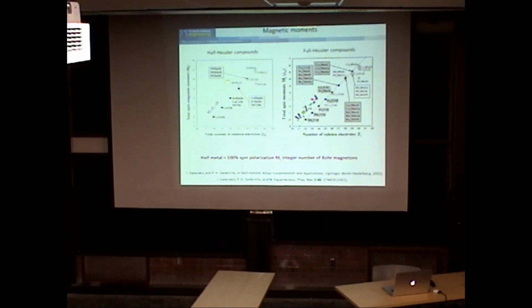You can go further. If I wanted a half metal, that means it should have an integer number of Bohr magnetons per formula unit. If I take the number of valence electrons and just keep adding, going from titanium to vanadium, I add one, so I should have one Bohr magneton, and it should be a half metal. You can see these are for the half-Heuslers. The important number is that the number of Bohr magnetons should be the number of valence electrons minus 18. For the full-Heuslers, it's the number minus 24. And you can see a nice one I'm going to be coming back to a lot, cobalt-2 manganese silicon, which is supposed to be a half metal with about 5 Bohr magnetons per formula unit.